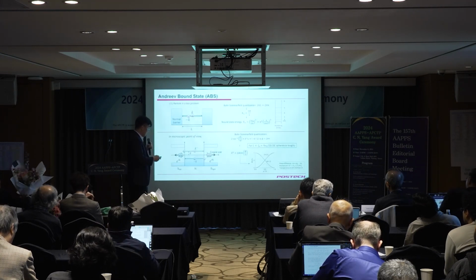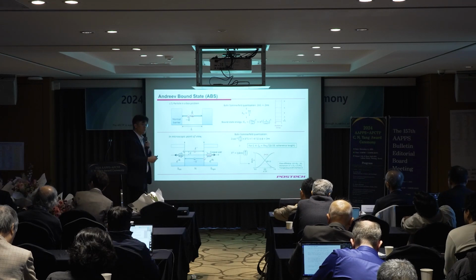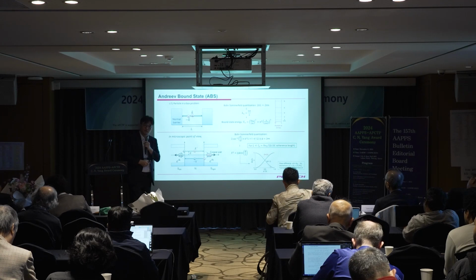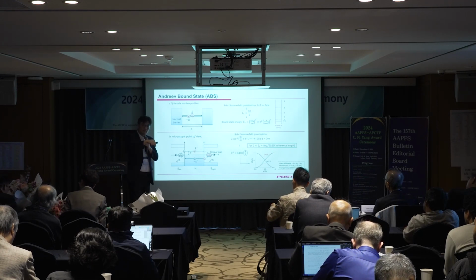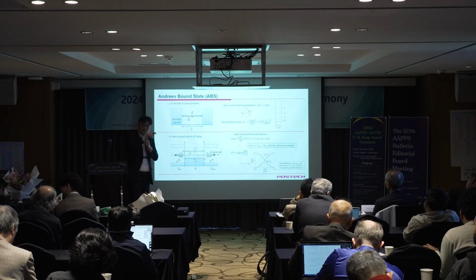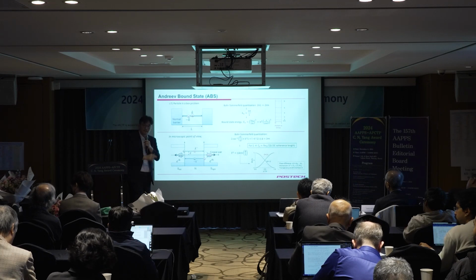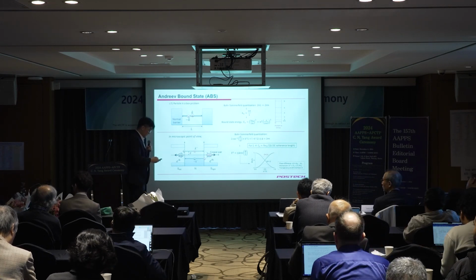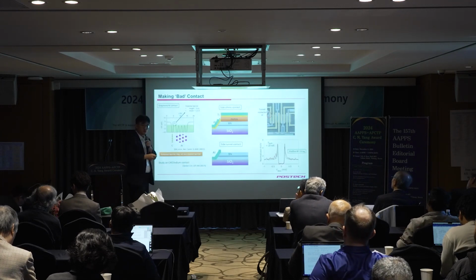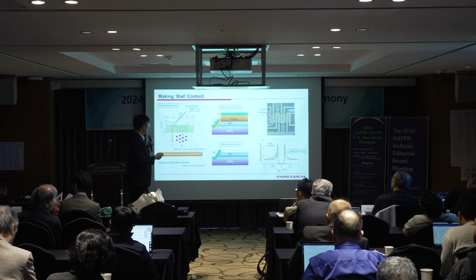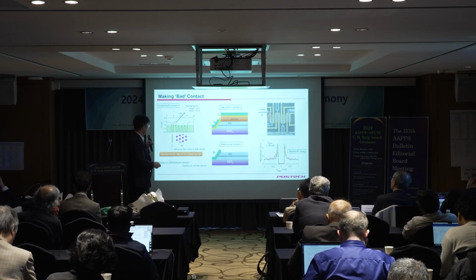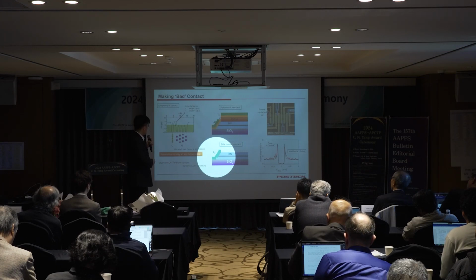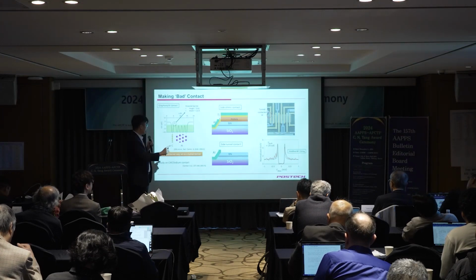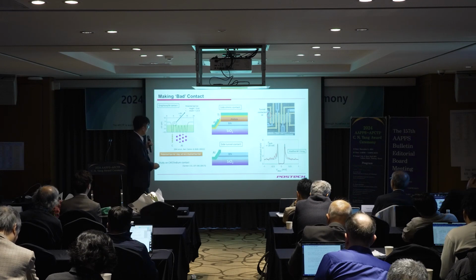And experimentally, to see the Andreev bound state, we need some kind of tunneling spectroscopy, like STM people do. They use tunneling spectroscopy on the surface of some unknown material and measure the energy-dependent differential conductance, which gives us the energy-dependent density of states. Because graphene is a 2D material, our idea to make this tunneling probe is to put some superconducting material on the side of the graphene and make a tunneling contact to the graphene, so that this aluminum side tunneling contact acts as a probe that can probe the density of states of the Andreev bound state formed inside the graphene.